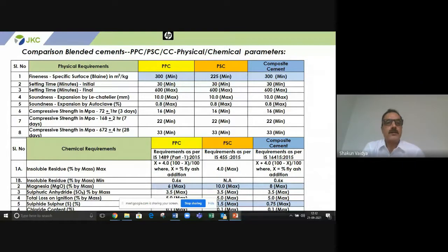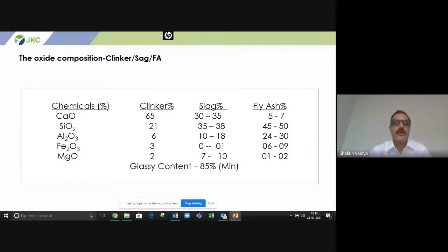So in a nutshell, in the comparison between PSC, PPC and composite, you can see that it is almost similar, barring the chemical requirements where we do not mix fly ash. So this X factor is not there in PSC. Otherwise, other parameters are almost similar. The only requirement of a supplementary cementitious material is that it has to be rich in silica, or rich in lime, or rich in both lime and silica. This table was earlier also displayed. So slag should be rich in both lime and silica, and fly ash rich in silica.